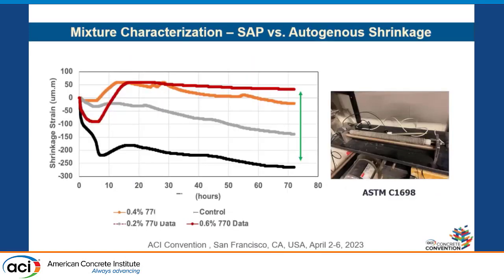But this is not from the printed elements. The results are out, but I'm not sharing them here. This is the autogenous shrinkage of the associated mortar to our printable mixtures. And you can see that when we add SAP, the autogenous shrinkage is decreasing, and even when we have 0.6% of SAP, we have a little bit of expansion, which we can say can compensate and inhibit the shrinkage in 3D printed concrete.